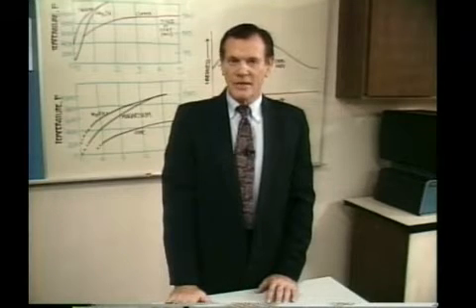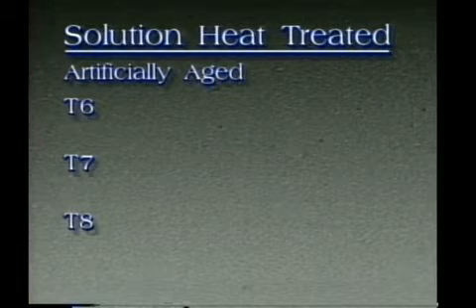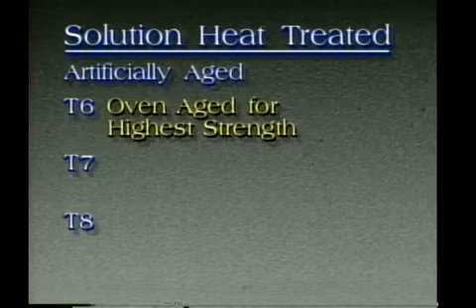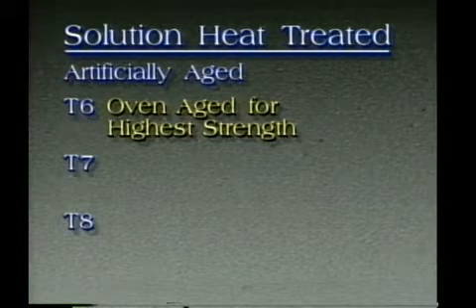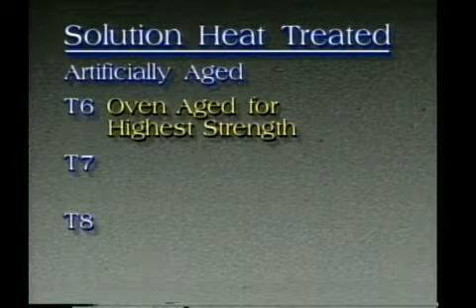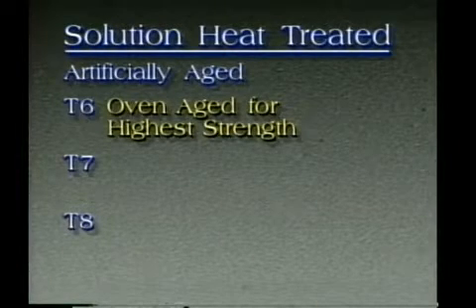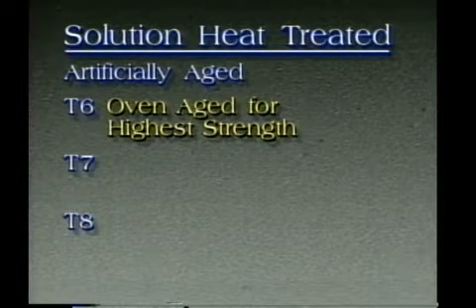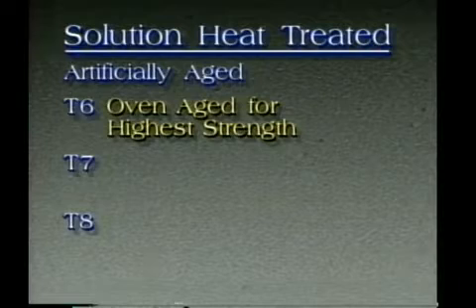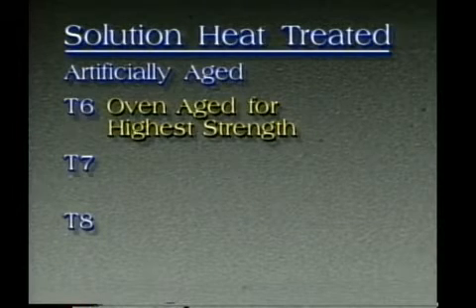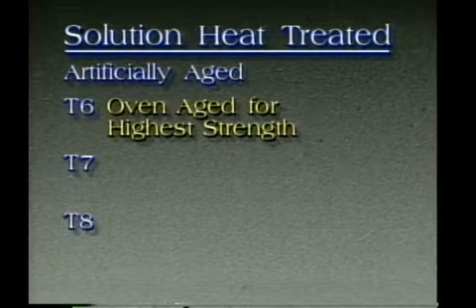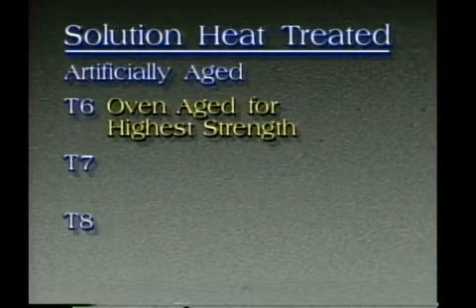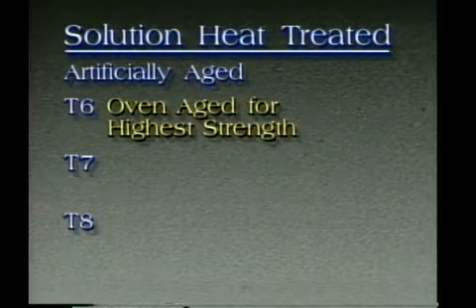The T6, T7, and T8 tempers require artificial aging in an oven or furnace in order to achieve the required level of properties. The differences between the T6, T7, and T8 tempers are as follows. The T6 temper requires furnace or oven aging using appropriate times and temperatures so that without cold work, the highest possible level of tensile properties is obtained. In the case of some alloys, such as some commercial castings, the material may be underaged in order to retain a usable level of ductility. For wrought alloys, in most cases, the T6 temper usually represents the highest strength possible for a given alloy.